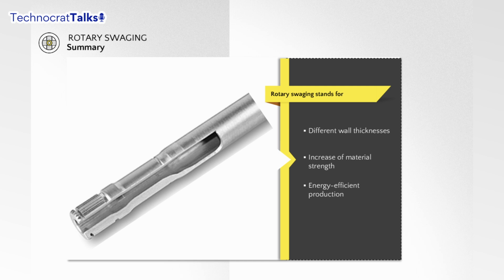First of all, yes, you have. Sometimes we are quite good at overcoming this issue. These irregularities are more or less in the range of several tenths of millimeters. So 0.1, something like that, or 0.2 if we are talking about small wall thicknesses. What we have seen on steering shafts is that customers do not take this off. Because the only possibility is that you make it a little bit longer, and then you simply cut it off, and then you have a similar length on all of them. At the beginning, we really did it like that until customers came to us and told us it's not even necessary. This is not a technical point, so this has no function. Whether it looks like a wave a little bit or whether it's completely round, we do not care. So this is the first case.